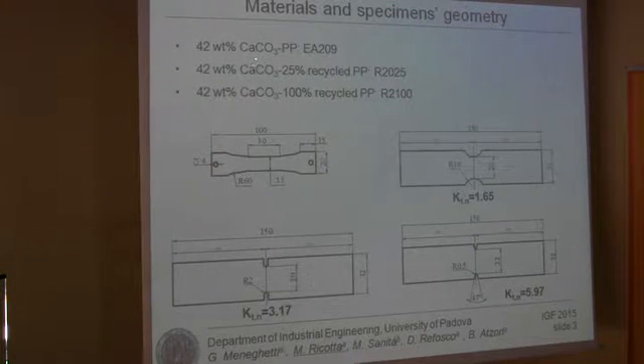A 42% weight calcium carbonate filled polypropylene, here named EA209; a 42% weight calcium carbonate filled polypropylene adding 25% of recycled polypropylene, here named R2025; and finally a calcium carbonate filled totally recycled polypropylene, here named R2100. The notch sensitivity was investigated by using three different geometries: a 10 mm semicircular notch, a 2 mm radius U notch, and a 0.5 mm radius U notch.